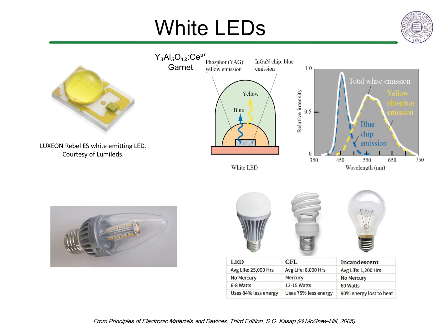LED lighting is poised to take over the lighting market because they are more efficient than conventional lighting, even fluorescent lighting. To get a broad spectrum of white light, phosphors are typically used. A common example is the use of a single blue LED, which not only provides blue light, but also excites a cerium-doped yttrium aluminum garnet phosphor, which has a broad band yellow emission that combines with the blue to produce white light. The polymer droplet acts as a lens to focus the light and protect the phosphor.